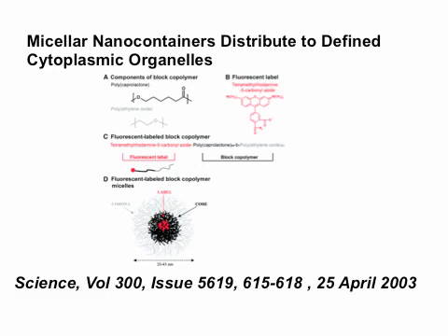So then you have a label which is fixed, and you have your micelle, but you still have the problem that if you dilute this, it might disintegrate, unless it's kinetically frozen. What do I mean by kinetically frozen? If the glass transition temperature of your hydrophobic part is really high, then you basically lock it, because it's like a solid then. And then obviously dissolving it might become a bit of a problem. So you could physically say, I'm going to make a hydrophobic part with a really high Tg, and then it's physically locked. Or you can say, I'm going to chemically cross-link it.